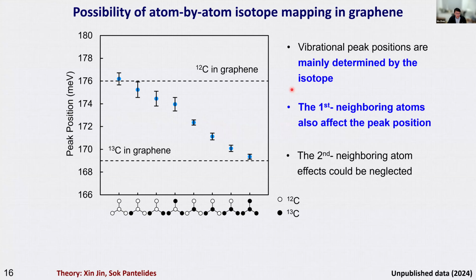So to do this, we understand that the vibrational frequency is mainly determined by the atoms you are looking at. But from the previous case, we also see that it's also affected by the neighboring atoms, especially the first nearest neighbor atoms bound directly to the target atom. So here we use DFT to calculate different types of structures, where the white atom is carbon-12 and the black one is carbon-13. So we have carbon-12 bonded with different numbers of carbon-13 atoms, and here's carbon-13 bonded with different numbers of carbon-12.